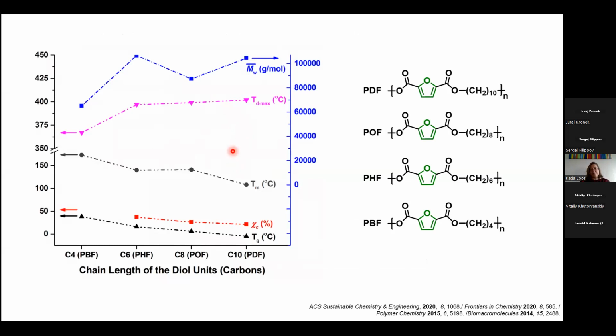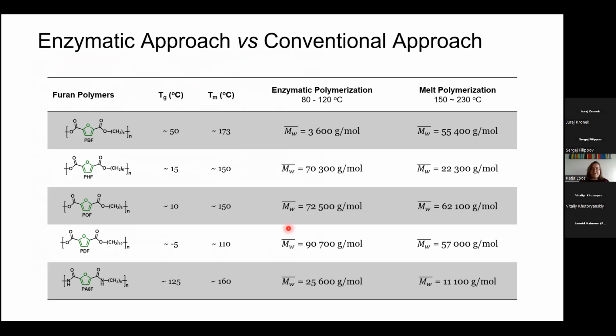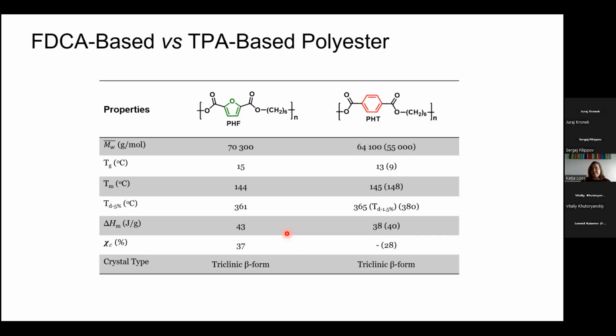But of course, they were replacing PET by PEF because it looks the same. But I think there would be other polymers which might be even better to introduce to industry to replace PET than PEF. And one thing which amazed us in the beginning, that in these reactions we sometimes even get higher molecular weights than the normal melt polycondensation. Because what people always complain about, and which is in most cases also true, I have to confess, is that we get lower molecular weights than a normal melt polycondensation. But if you, for instance, look at this PDF polymer, then yeah, we get higher molecular weights. And if you compare the properties of the comparable polymers, they are more or less the same.